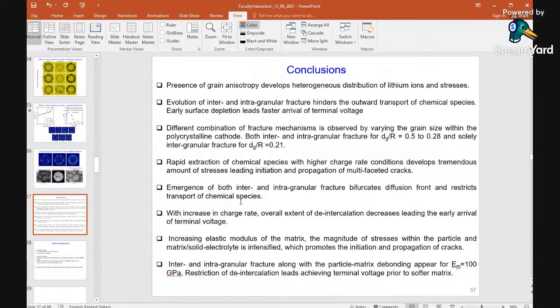We see that the grain anisotropy develops a complex heterogeneous distribution of the stress field. It develops inter- and intragranular fracture, which essentially interacts with the transport process. We see that different types of cracks are observed with different grain sizes. We have studied the development of multifaceted cracks. We saw that both inter- and intragranular fracture restrict the transport. We have seen that matrix modulus plays a very important role in determining the fate of the capacity for this structure.